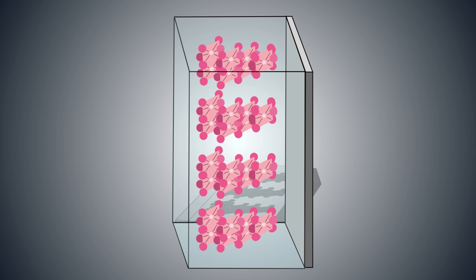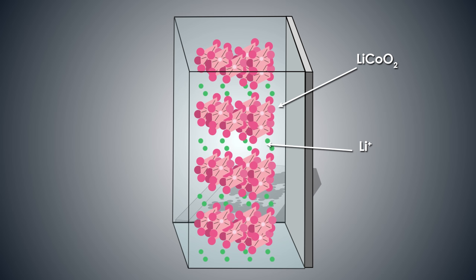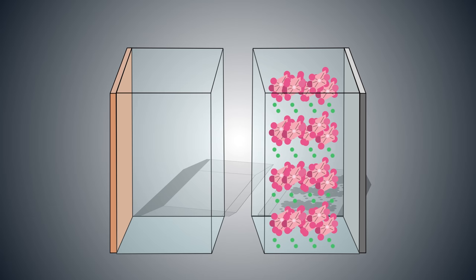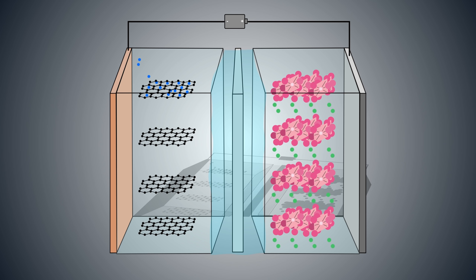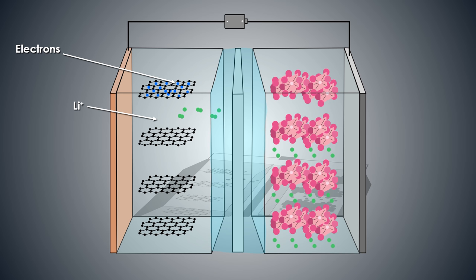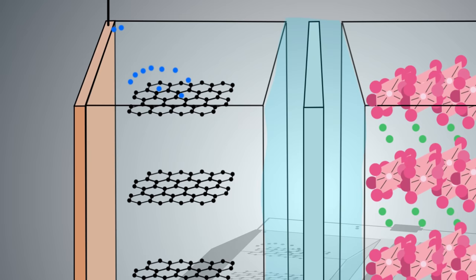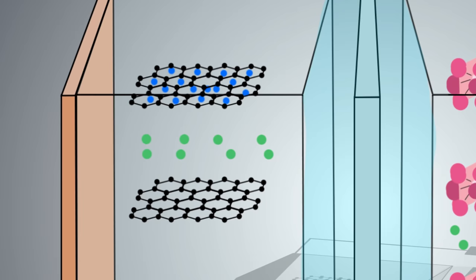Look, here is a rough diagram of such a lithium-ion battery. There is a mix of different metal oxides, for instance cobalt and lithium oxides, which are placed on cathode aluminum foil and form areas with lithium ions between cobalt oxides. If we complement this diagram and add an anode made of copper foil and cover it in graphite, and add an electrolyte between the cathode and anode, then energized lithium ions will be able to travel to the graphite. These processes happen when the accumulator gets charged. Upon full charging, almost all lithium ions have stuck to the graphite, which acts as a frame for all lithium ions to stick to.